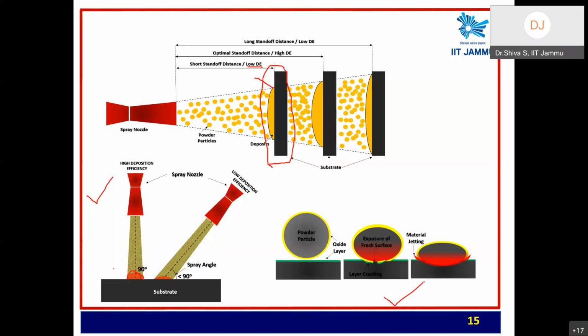It is not just oxide. At times there is also formation of nitrides, because you are using nitrogen here, and that forms a thin layer around the powder particle. This thin layer of nitrides will start exposing themselves on the surface, and you will find that they are breaking, and that impingement is not sufficiently taking place due to the presence of this yellow layer.